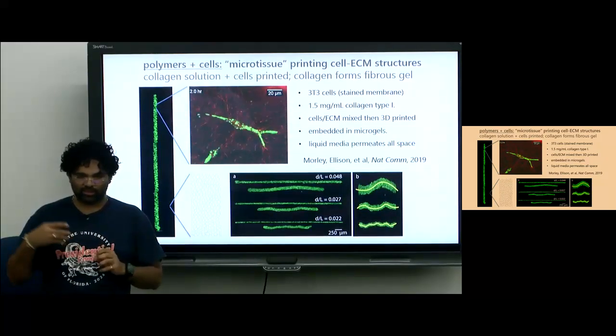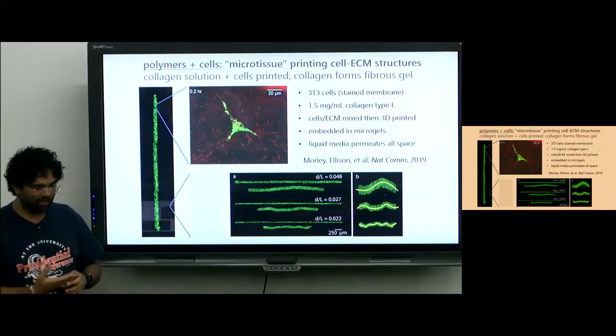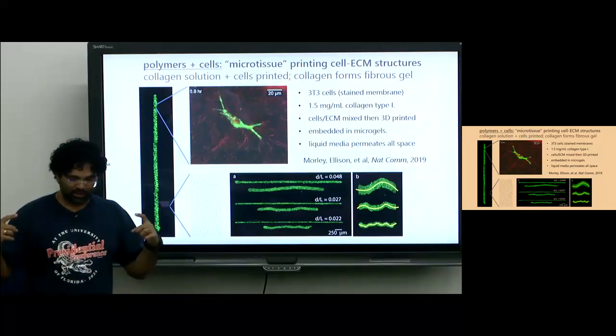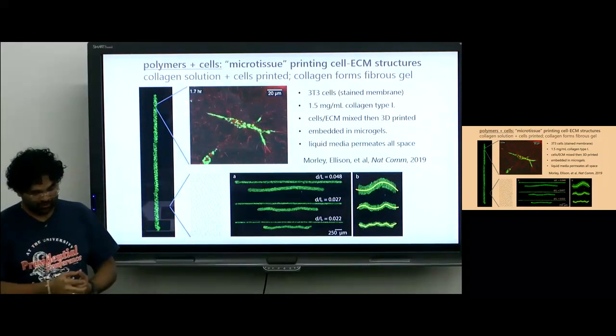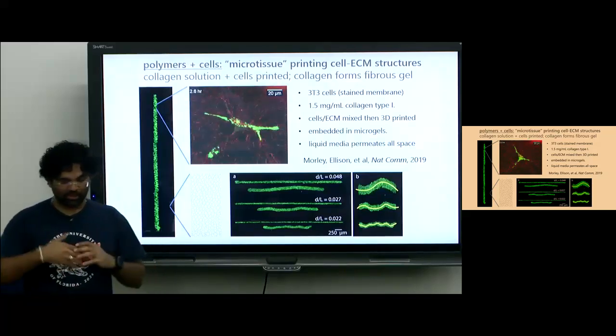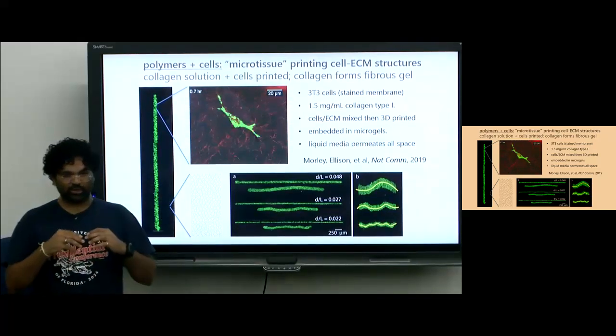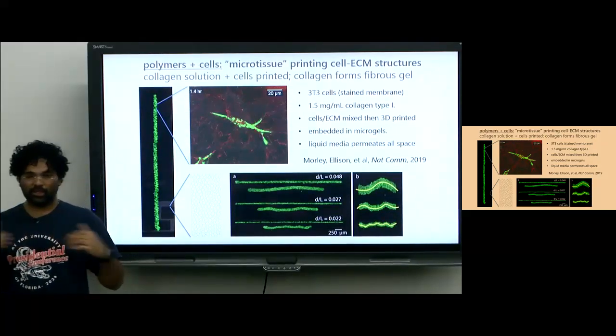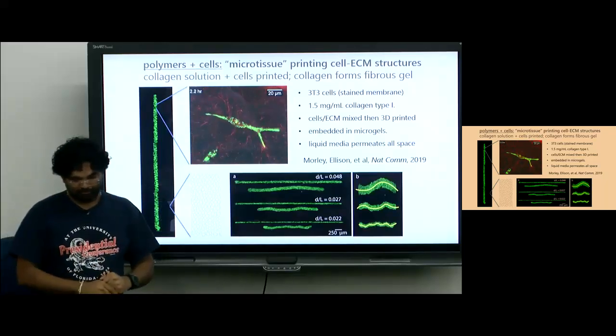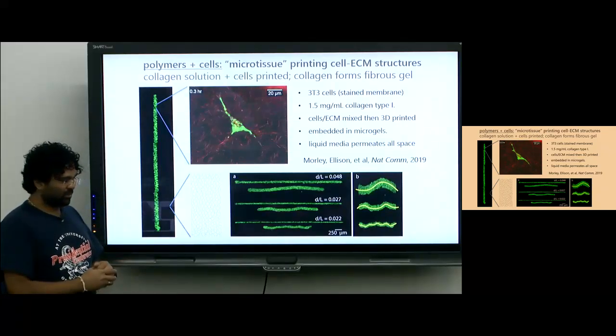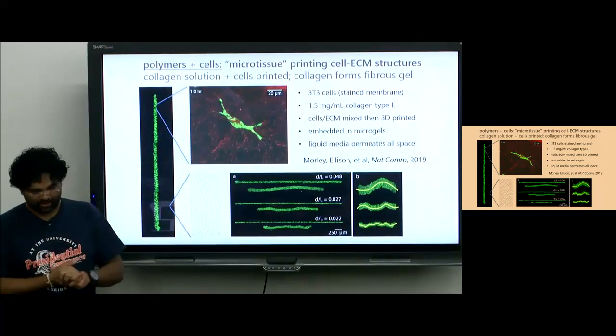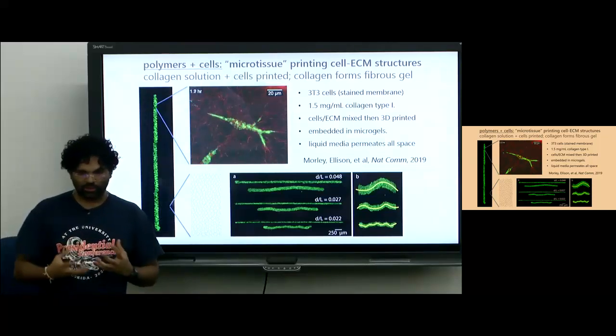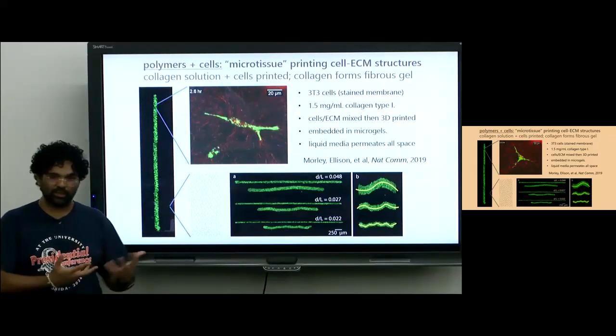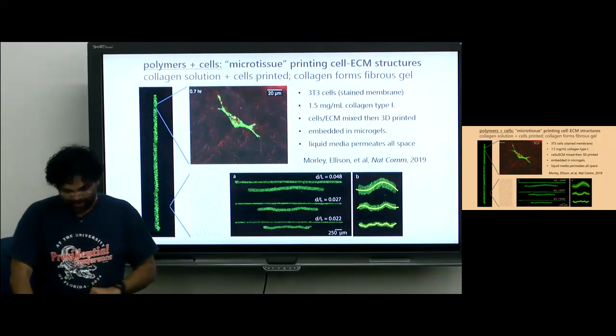A couple of previous students, Cameron Morley and Tori Ellison, printed these little beams, which are mixtures of these 3T3 cells with collagen. They then observed buckling of the beams, which was really neat. The buckling seemed to be controlled by your aspect ratio, the diameter to length ratio. And these were printed into microgels, which were swollen in a liquid growth media that the cells need to proliferate, right?